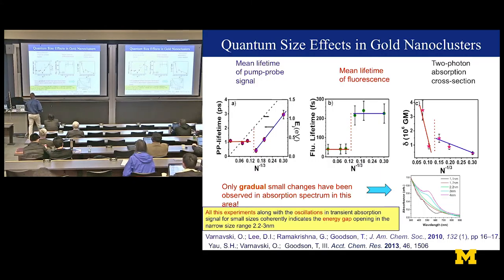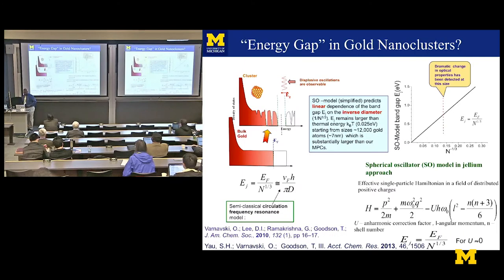And Sunghai was in Jülich, and you'll see we're important in trying to come up with a model. Here's the bulk gold, here's the cluster. You're making this bulk gold smaller and smaller and smaller until finally it gets so small that you get this opening. So this spherical oscillator model predicts that there's a linear dependence on the band gap, which is inversely proportional to the diameter. And so for the case of gold, you can try to use this so-called single particle Hamiltonian to calculate where that energy would be and where that size would be. And so it's somewhere in the vicinity of less than 2 nanometers.